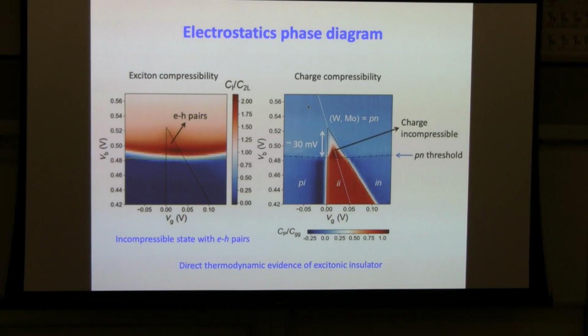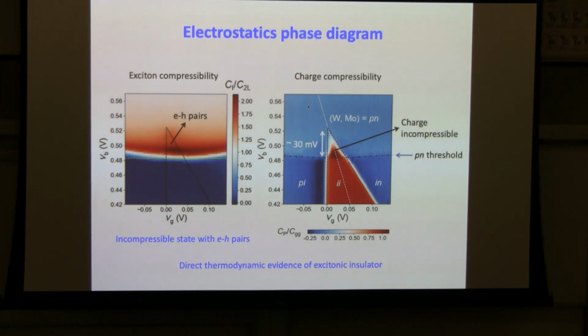Okay, so now we can put everything together. On the right-hand side is the charge compressibility. On the left-hand side is the exciton compressibility. And remember that the charge compressibility, the red region, means that it's charge incompressible. We have a charge gap. It's an insulator. But you can see that inside this triangle, while the system is in an incompressible state, the exciton is compressible, meaning that there are really electron-hole pairs in this system. So it really provides direct thermodynamic evidence of an excitonic insulator: we have a state that has a charge gap, but there is a fluid of excitons that are already populated inside this triangle.